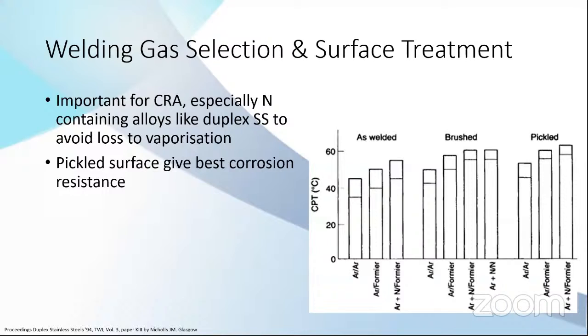So, welding gas selection: some alloys have nitrogen content in the metals. Nitrogen is very volatile, so when you weld, the nitrogen can escape to the atmosphere. Sometimes you need to add nitrogen gas in the shielding or in the backing gas to avoid nitrogen loss to the atmosphere. When you have nitrogen loss, for example in duplex stainless, which is highly alloyed with nitrogen, it reduces the corrosion resistance a lot.